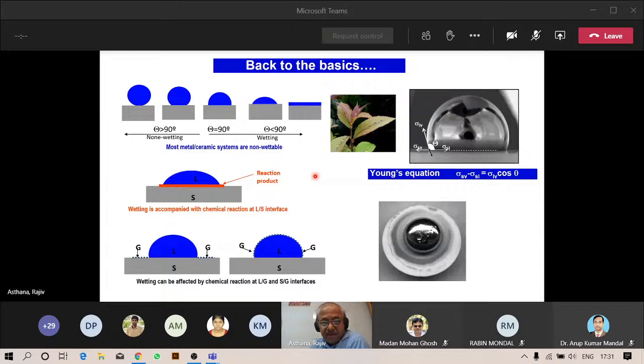Not so with high temperature systems. When you have liquid aluminum sitting on a solid ceramic surface, the droplet can continue to spread for half an hour or 1 hour, provided, of course, you control the cooling conditions, the temperature, and other things here. And the reason for that difference in behavior between low temperature systems and high temperature systems is that there's continuous interaction going on between the liquid and the solid that could be modifying the surface ahead of the liquid. So the reaction layer could be spreading ahead of the liquid. It could cause roughening or other changes.